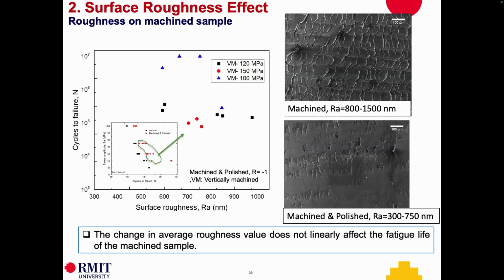Then we looked at surface effect in more detail, machined versus machined and polished, and we can see these are vertically machined samples. What we found, the change in surface roughness value, there is no easy shortcut linear way to scale or apply similitude to predict the performance. You can see it's scattered all over the place. At a higher loading, you can observe some close values, not so much scattered, but at a lower loading, such as black dots, although the roughness values are very much scattered from 500 to 1,000, the fatigue performance are nearly the same. Okay, so it doesn't scale linearly with the roughness.